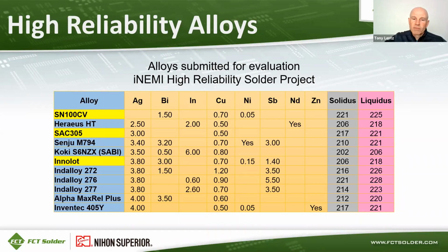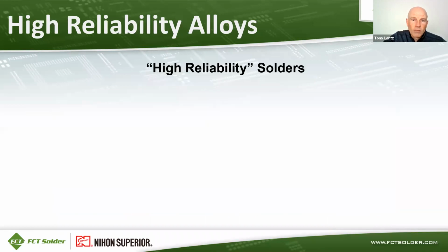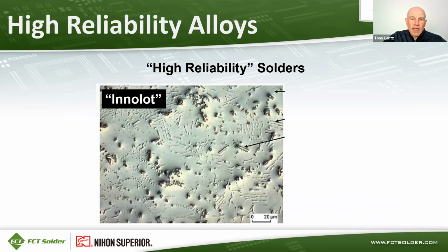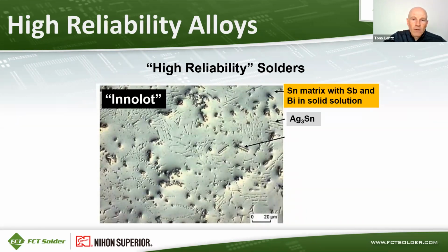type automotive applications. Now, the interesting thing about providing an alloy without silver like SN100CV is the cost of silver has been rising dramatically over the last several months. And so the costs of any of the silver containing alloys, of course, might become prohibitive for certain users, whereas silver-free alloys might be an interesting option for them. So high reliability solders like Innolot have a cross section that looks like this. There's a tin matrix with antimony and bismuth in solid solution. Then there are Ag3Sn intermetallic particles which precipitate out, as well as the Cu6Sn5 (copper 6 tin 5) particles which precipitate out.